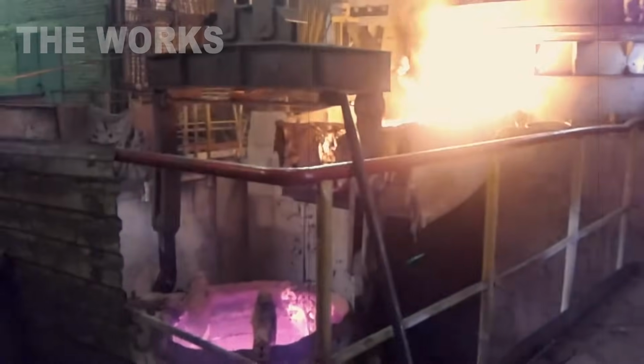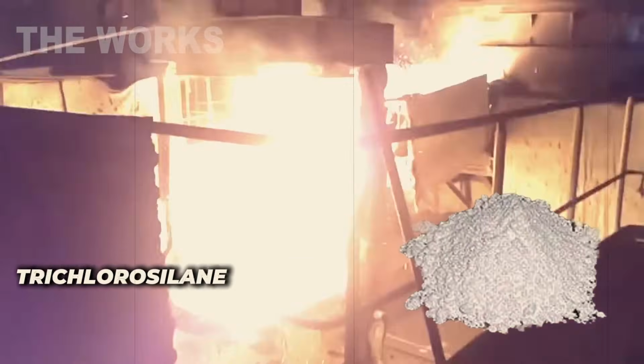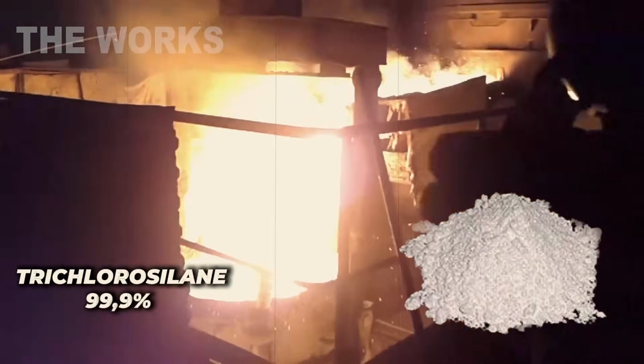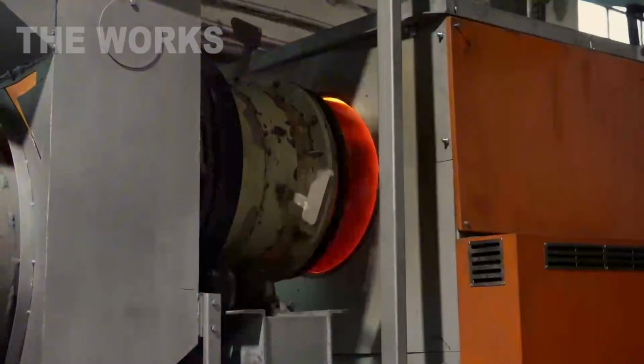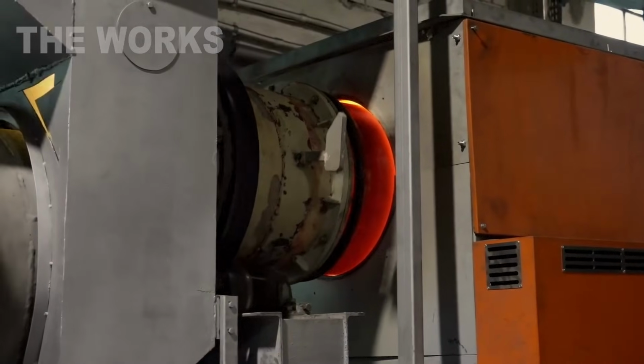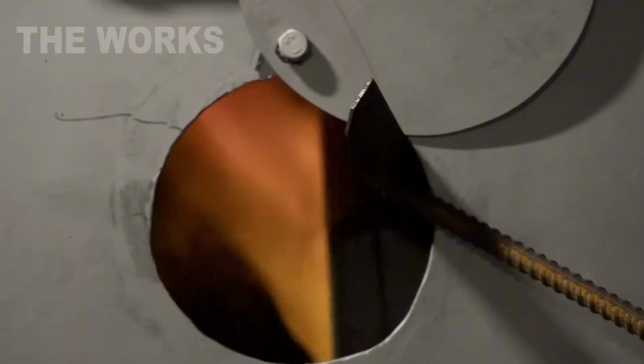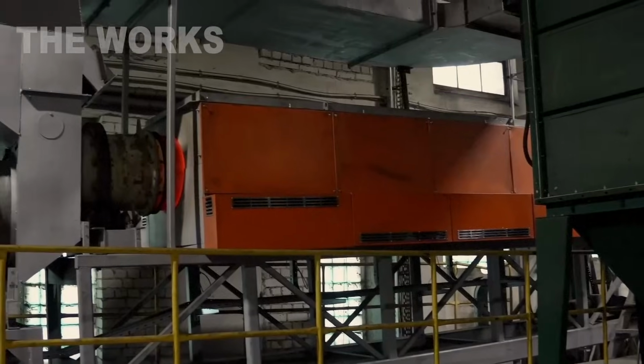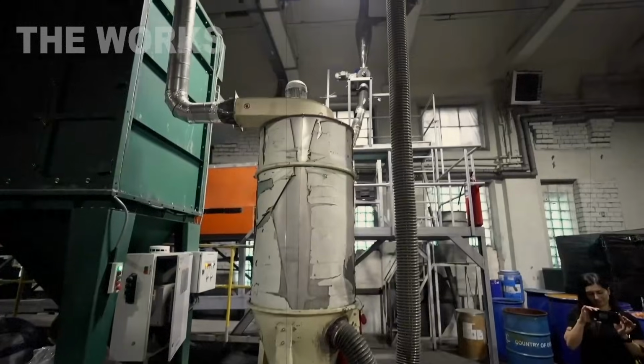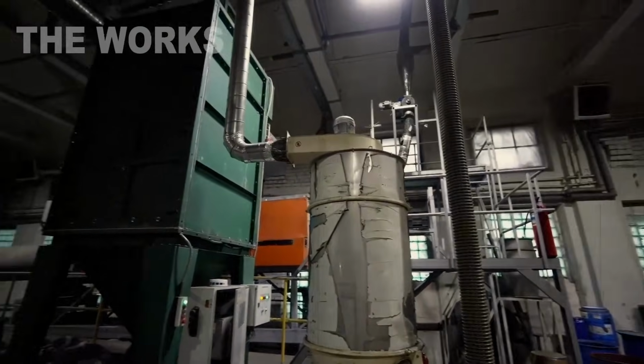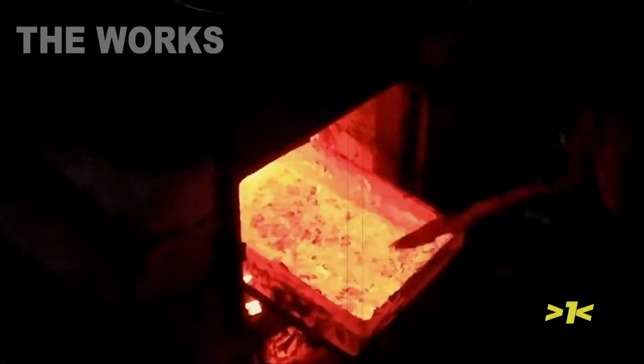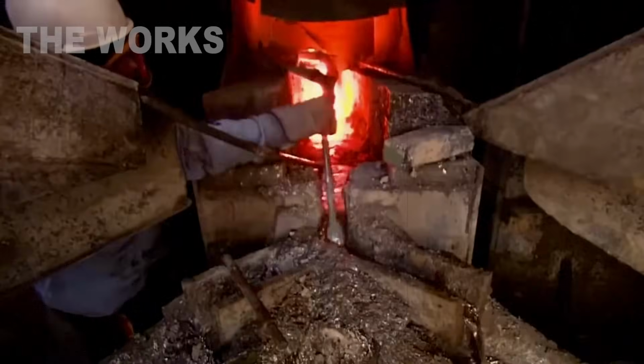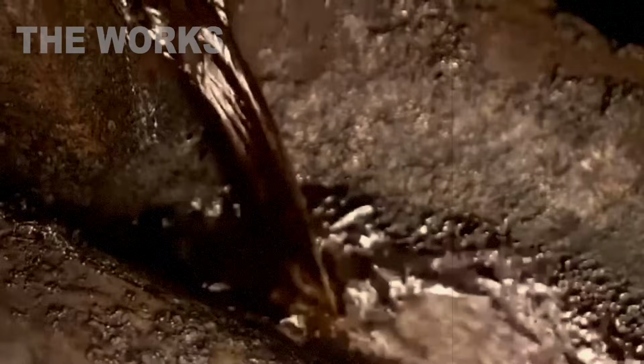Now you need to turn it back into pure silicon. That's where the Siemens process comes in, one of the most beautiful and complex in metallurgy. Inside a sealed reactor, they install thin silicon seed rods. Purified trichlorosilane is fed in along with hydrogen and heated to 2,000 degrees Fahrenheit. At that temperature, the trichlorosilane breaks down and pure silicon deposits onto the seeds, building them up layer by layer, atom by atom. The process runs for several days.